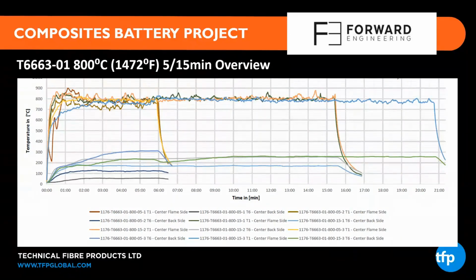So let's look at the actual results on the graph. Apologies, this graph is a little bit busy, but it summarizes the thermal results with Technofire T666301, which is a 70 gram per square meter Technofire grade at 0.37 millimeters thickness. So really thin, lightweight fire protection material. Time is on the x-axis and temperature is on the y-axis.